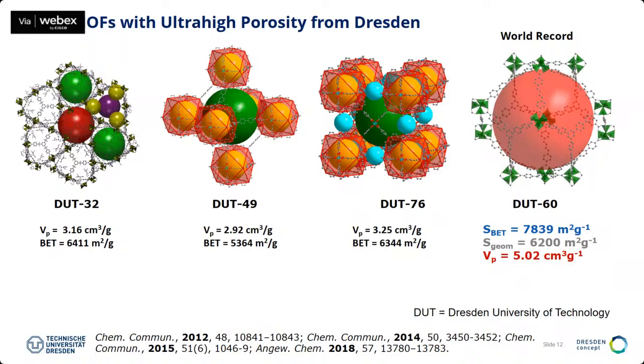And these are some of the materials. I will come to that later also. They have record porosities, 6,000 or even 7,800 square meters per gram. And this is the material DUT-60, which currently still is the world record in terms of porosity. And this also creates debates, of course. Is the BET theory still valid? We have here some experts in how you calculate these surface areas.